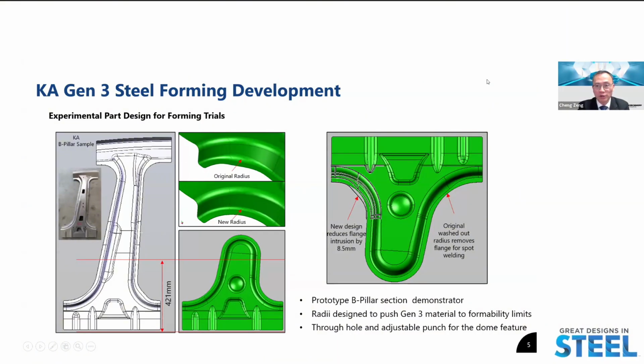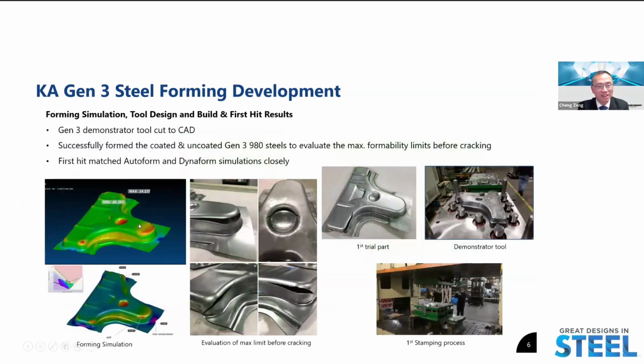Okay, so when we did the simulation, you will see on the next slide, those hot spots, which are stress concentration areas. And that's exactly what we intend to do: try to evaluate what the minimum radius could be and what kind of materials can be stretched out. We did the forming simulations and highlighted a few hot spots, and then we did the tool build and trial. And you can see here it correlated very well, cracking exactly at the location we predicted during the forming simulation. We did it in AutoForm in-house as well as in the tool shop with the Dynaform simulation. They correlate very closely, and this is the first hit, the tool build, and the first stamping process we did during the pandemic in 2020.